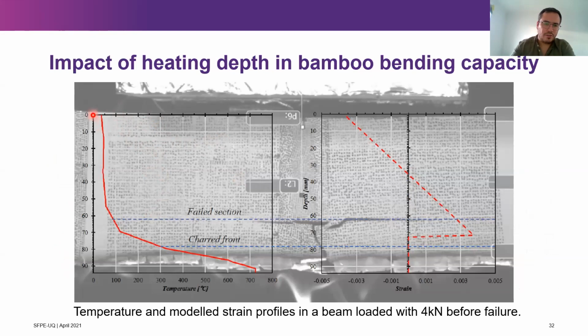When you look at the results here, this is the temperature profile of your beam. So you have temperature against depth. That's the depth of the beam at the back. And you can see that the char front, if we use the conventional approach that we currently use in timber, which is assuming that the 300 degrees isotherm is what defines the char depth, right? You see that the failure occurs way above that char front, right? And this is because of the influence of the heated depth. We observe that bamboo has a significant reduction at very low temperatures, still a significant reduction below 100 degrees. This is for tension. Remember that this is the side that is exposed.